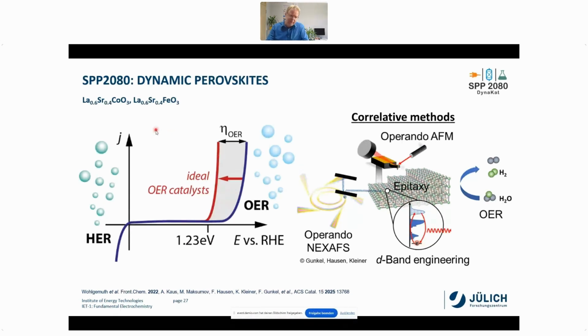And water splitting devices become more and more important to get our green hydrogen produced, whereas the hydrogen evolution reaction, HER, is not really the issue because there's only a low overpotential. But if we look at the positive reaction side here, the oxygen evolution reaction, then thermodynamically this would happen at 1.23 volts. But we see that we have a huge overpotential for the current materials we have. So we need a lot of energy, and we would try to minimize this overpotential for the oxygen evolution reaction to get really good water splitting devices.